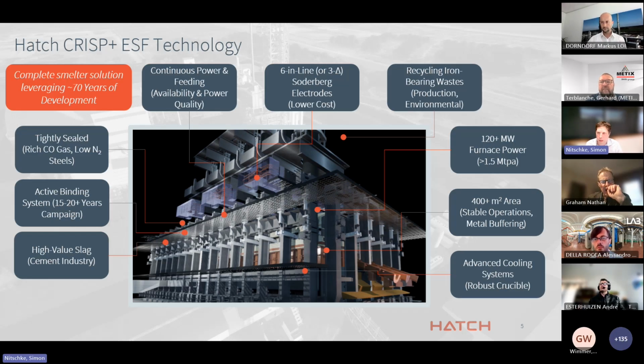We've got tight sealing of that upper gas space above the liquid bath, and that's important for providing a CO-rich off-gas stream and opening up the possibility and value of integrating low nitrogen steel production out of ESFs. It's continuous operation, as we've mentioned earlier, which leads to high availability and less complexity in terms of integrating into industrial power grids, particularly weaker grids.